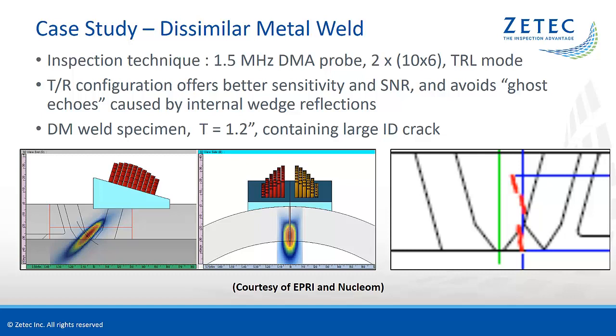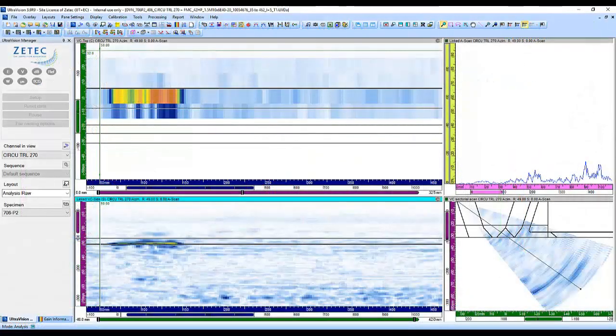The image on this slide shows the acoustic beam for standard phased array focused near the ID surface and the intended morphology of the branched ID crack. For this laboratory study, we decided to record elementary FMC data together with a standard phased array channel set up according to existing best practice, with L-wave beams from 35 to 70 degrees. The probe was used at full aperture for both techniques.